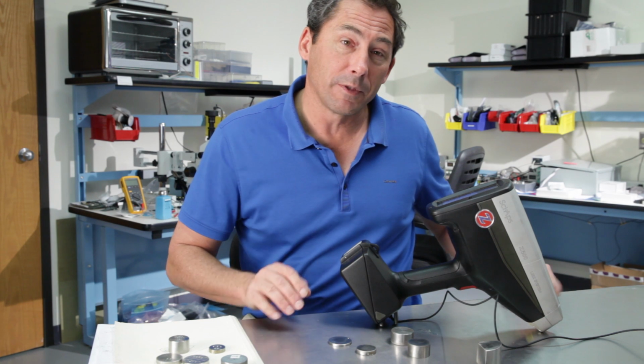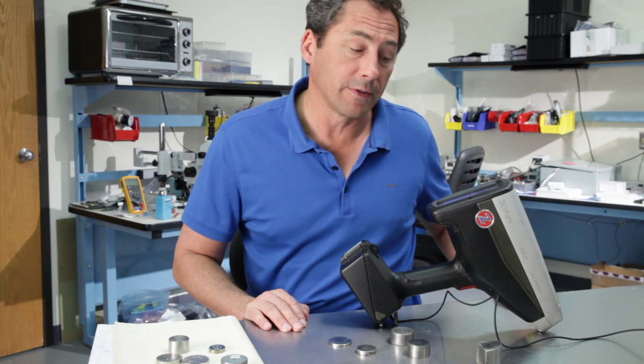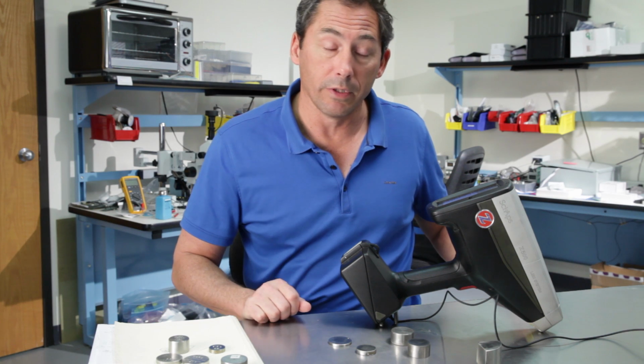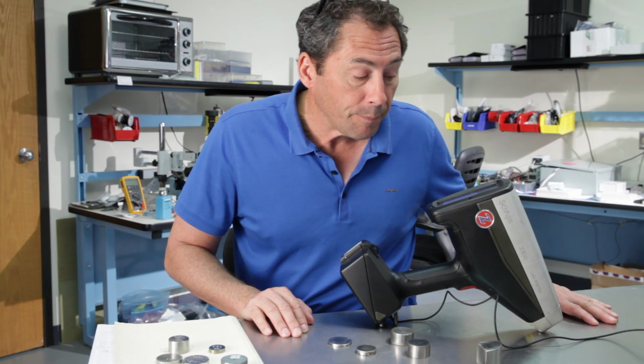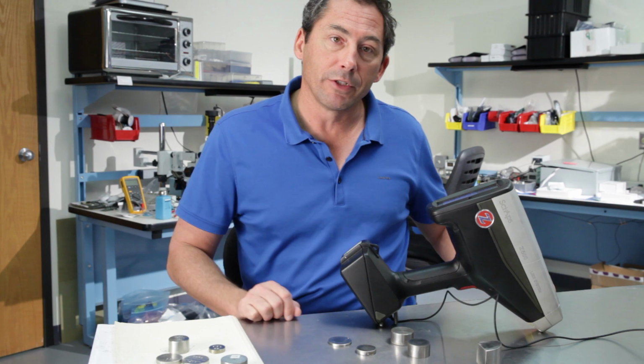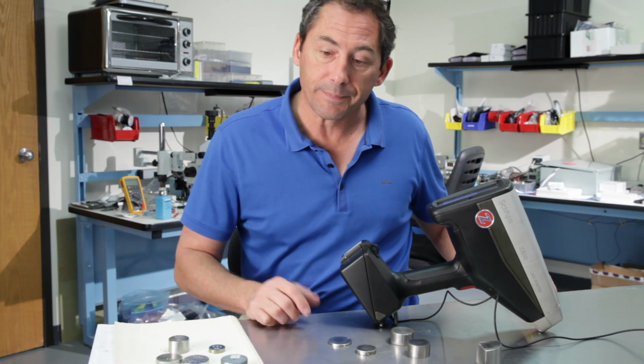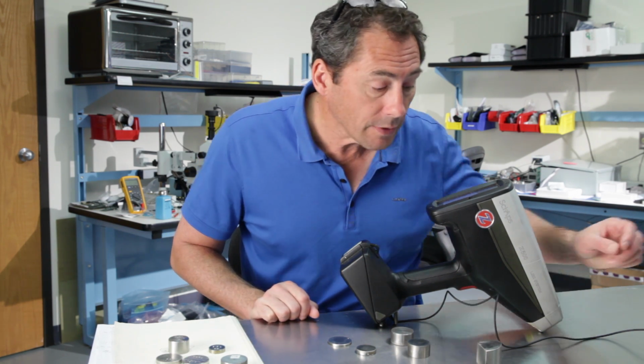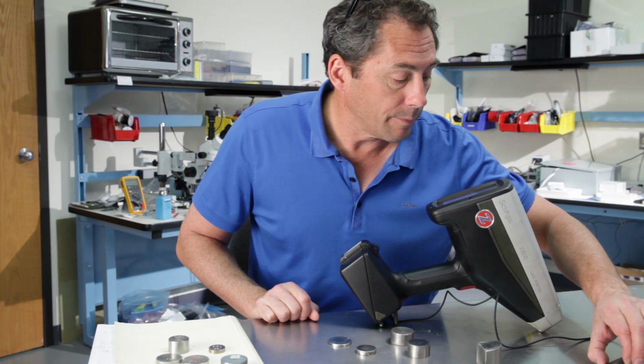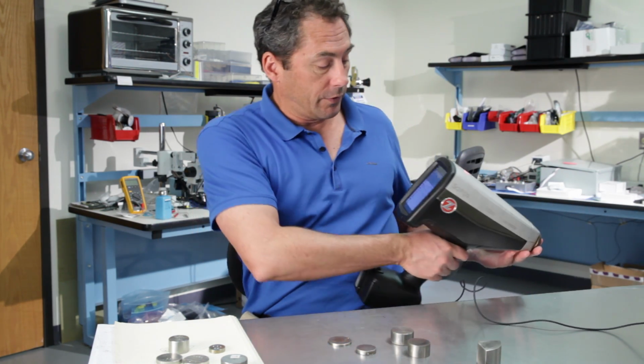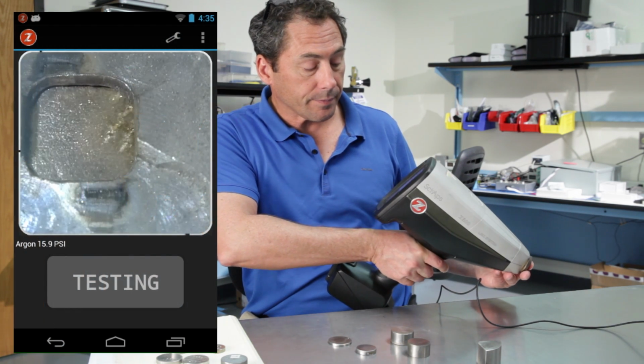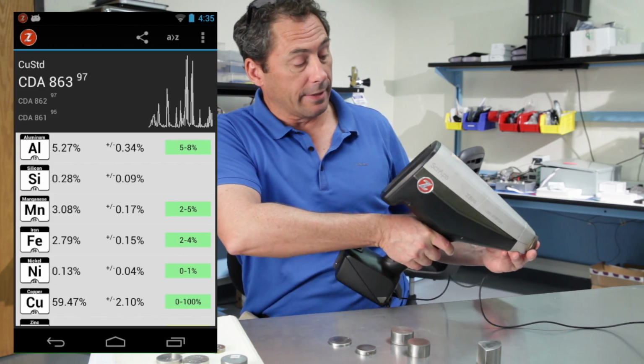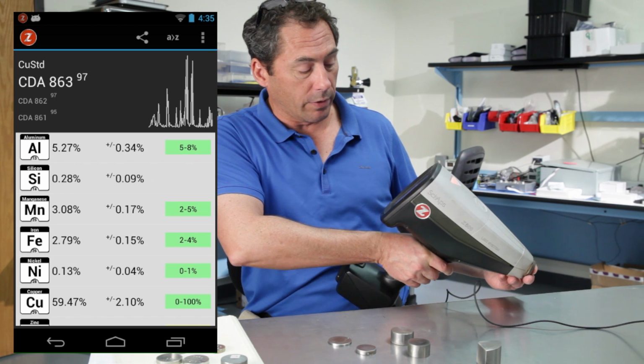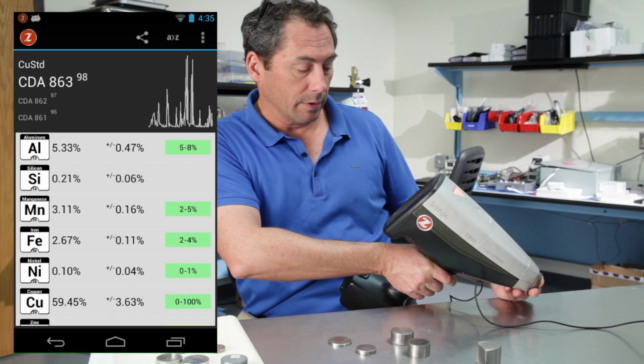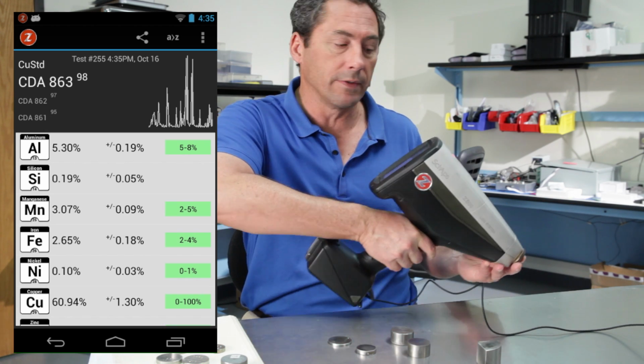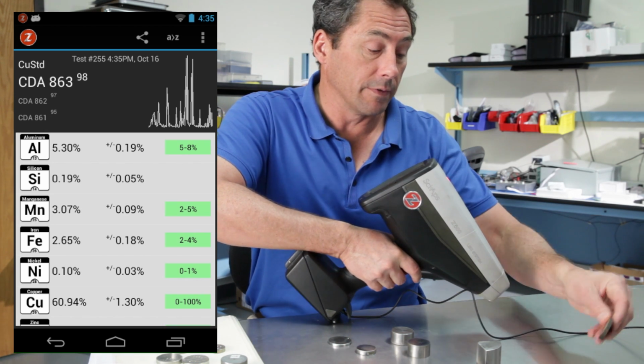Another big area where you pick up speed in sorting and material processing on these copper alloys is your aluminum bronzes and your silicon bronzes. And that's because, again, LIBS measures the aluminum and the silicon very quickly compared to X-ray. So take a typical aluminum bronze, and you'll see in just a couple of seconds the aluminum reading comes up. It identifies it as 863, which is what it is, around 5 or 6% aluminum, so a little bit of silicon. So there's your aluminum bronze. Very, very quick reading, just in a couple of seconds.